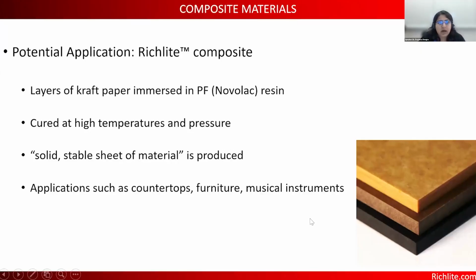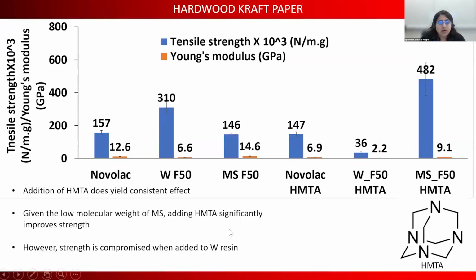So we decided to check if our resin would be suitable for such an application, and how it would compare in terms of mechanical properties. So I started with hardwood kraft paper, similar to the glass fiber strips. Hardwood kraft paper was cut into strips, immersed in the resin acetone water solution, and then subjected to tensile testing. As you can see, we tested it with the HMTA, which is the commercial crosslinker that is used in Novolac synthesis as well. So we tested it with the HMTA crosslinker and without it.